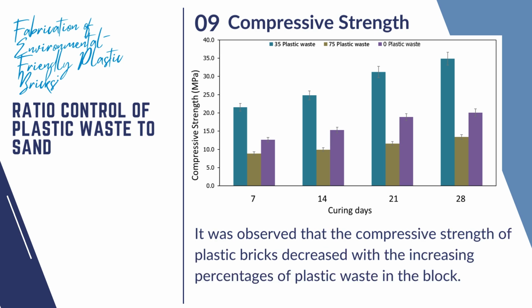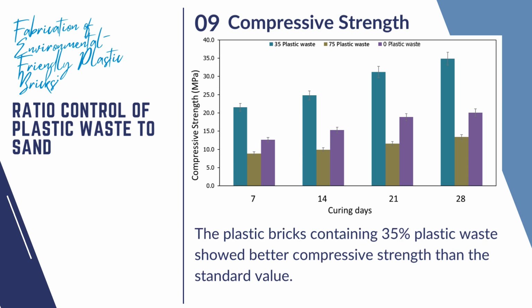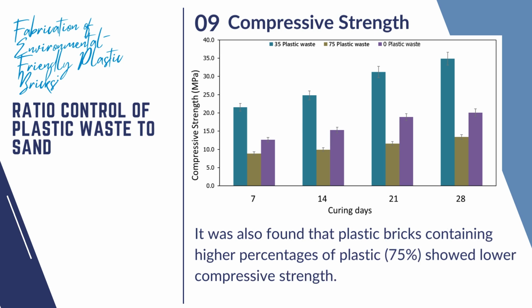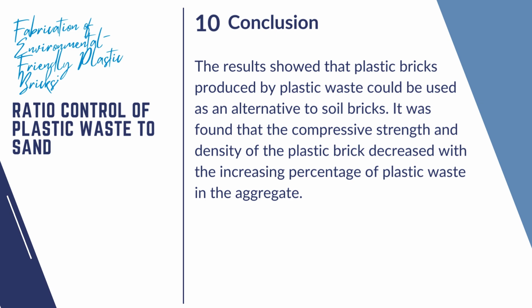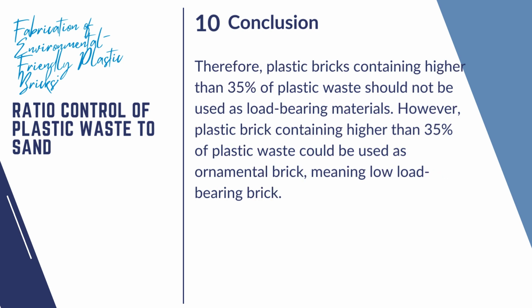It was observed that the compressive strength of plastic bricks decreased with the increasing percentages of plastic waste in the block. The plastic bricks containing 35% plastic waste showed better compressive strength than the standard value. It was also found that plastic bricks, containing higher percentages of plastic, 75%, showed lower compressive strength. The results showed that plastic bricks produced by plastic waste could be used as an alternative to soil bricks. It was found that the compressive strength and density of the plastic brick decreased with the increasing percentage of plastic waste in the aggregate. Therefore, plastic bricks containing higher than 35% of plastic waste should not be used as load-bearing materials. However, plastic brick containing higher than 35% of plastic waste could be used as ornamental brick, meaning low load-bearing brick.